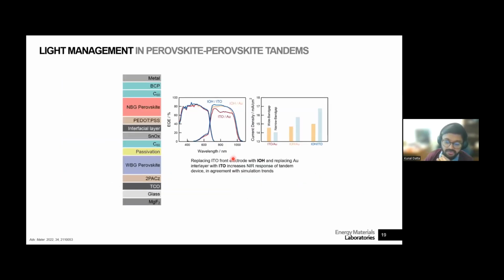And if you try to do that in the experiment itself, you start to see the same behavior. That indeed this is the reference. So ITO here and gold here. And then when you change the ITO for IOH, you increase the near-infrared transmission. So the EQE response here goes up. And then when you replace this gold layer for ITO, this part also improves, right? And as a result, in the current